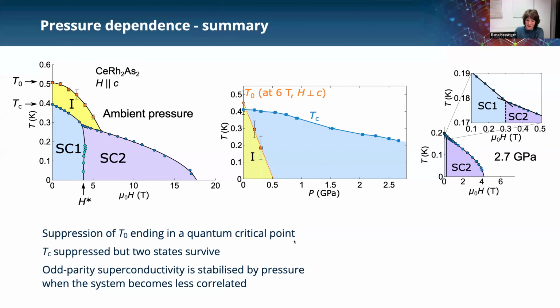But just to say one thing, you said spin triplet, but this is actually pseudo spin triplet, because the odd parity comes from this interlayer degree of freedom, which is then the pseudo spin. And in that pseudo spin, it's a triplet. The pairing itself can be dominantly singlet pairing, but still you can have these two superconducting phases by the change of the sign of the gap between the layers.